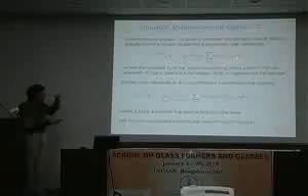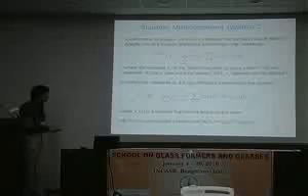Okay. Last thing, so these are multi-component systems, but realize that if you have just a one-component system, so nu equal 1, all these factors here cancel, and indeed you find that the neutron scattering function is equal to the static structure factor, S of Q. So if you have just a one-component system, whatever you do, as long as you do it correctly, neutron or X-ray, it gives you the same answer. So this is the good news for one-component systems. So how does this look like, this multi-component system?